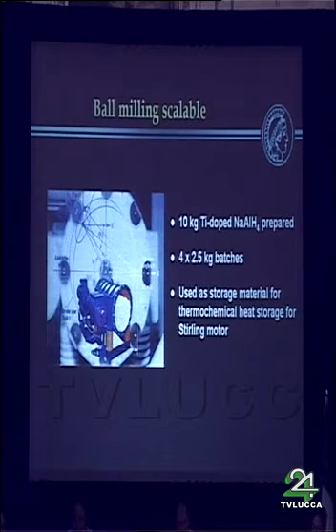This ball milling is in fact scalable. We have produced in our laboratory a 10 kilogram batch of titanium-doped sodium alanate in 4 smaller batches, so 4 times 2.5 kilogram batches. That was not used as a hydrogen storage material, or hydrogen storage was only a secondary effect. This was used as a thermochemical heat storage material for a Stirling motor. But the hydrogen adsorption and desorption properties of this 10 kilogram batch were pretty much the same as the properties of smaller batches, which we typically produce on the several gram scale. This is not our optimized material, but a material similarly produced on the gram scale has roughly identical properties. So it's a scalable process.